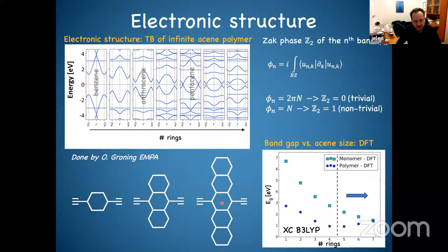Okay, so is it reality? First we do some calculations. And you see, this is just the tight-binding band structure for different polymers: benzene, anthracene, pentacene. And what you see is, again, there is a closing of the band gap, and then you open it again. So it means there should be some phase transition here. And here, these are the results of DFT calculations for the monomer, not the polymer, just these units like benzene, anthracene, pentacene, etc. And this is already the polymer.